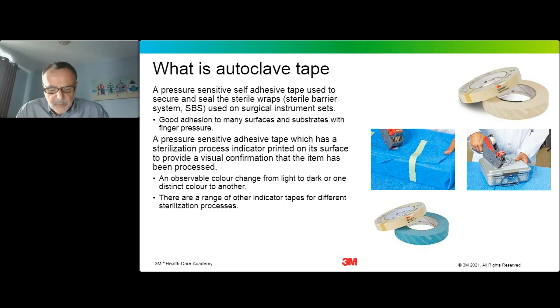What we mean by a pressure-sensitive adhesive is that it will stick to surfaces when it is placed on that surface and then moderate downward pressure is applied. Pressure is usually applied by the palm or finger and thumb, and this should be sufficient to initiate the adhesion of the tape to the surface. It should be noted that once tape is adhered to a surface, it will go through a maturation process and generally become stronger as the glue migrates into the surface to be bonded.